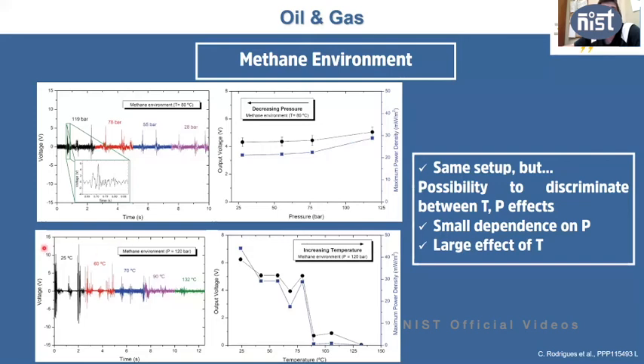If you increase the temperature, now you will have a very high effect. If you increase the temperature, the materials will degrade very fast at temperatures higher than 100 degrees. And so the temperature is the most important factor in reducing the output voltage that you get out of triboelectric nanogenerators in these environments. And so you need to come up with different materials that can avoid this effect.